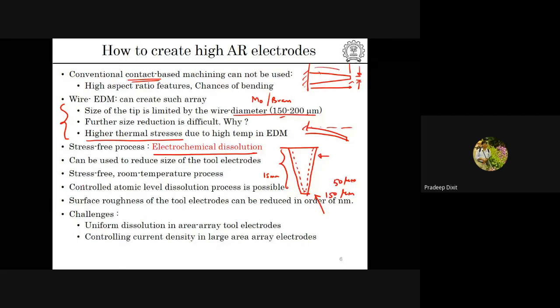Now the question here is why we have chosen electrochemical dissolution. Of course, electrochemical dissolution has a lot of advantages. The very first advantage is that this is a room temperature process. Typically all electrochemical machining processes are performed at room temperature or a slightly higher temperature, up to 40-45 degrees Celsius. Because of the low temperature, we do not have any kind of thermomechanical stress. It is also possible to go for controlled atomic level dissolution. For example, if you want to remove a few nanometers, in principle this is possible by using a very small current.